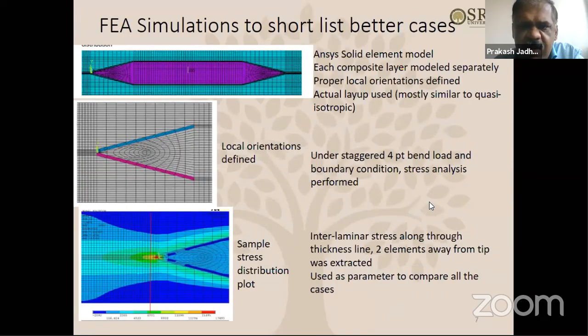Now talking about the simulation. For the coupon analysis, an ANSYS solid model was used. Its composite layers were modeled separately and proper local orientations were defined. As you know, every layer has a different orientation in the blade. Accordingly, we assigned the local coordinates and oriented each and every layer. The actual layup was used, a combination of zeros and 45s. Under the staggered 4-point bend load and boundary conditions, stress analysis was performed. So this is the sample stress and strain distribution plot.